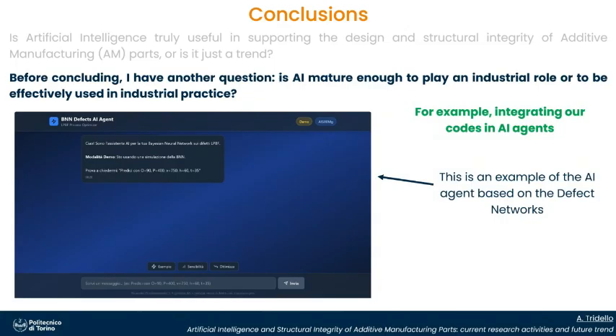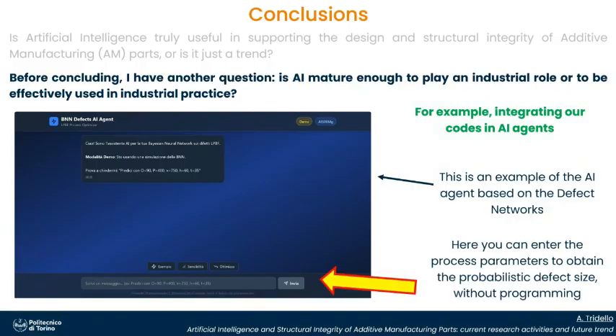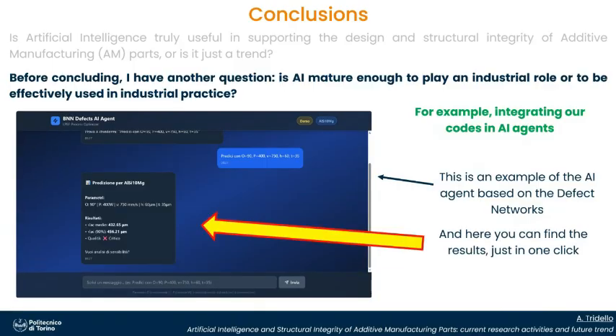This is an example of an AI agent based on a deep neural network, which I have developed very recently. Here you can prompt the process parameters to obtain the probabilistic defect size without any programming. This is not so beautiful, but the interface can be changed and become more readable, okay? And here you can find the results in just one click, okay? So if we have a tool like this, also for industrial application, we can exploit and boost the diffusion of the algorithms that we have developed, okay? But this is in progress, and this is a very, very recent activity, okay?